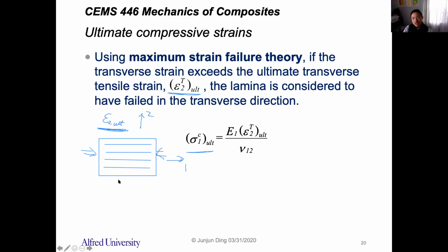which means the matrix or the matrix and fiber bonding fail, right? So let's see if this is the ultimate tensile strain of the matrix, right? So you don't want to exceed that. So by using this strain, you can calculate the maximum stress can be applied in this direction, right? So that's the ultimate strength of the composite in the transverse direction. So this is based on the failure mode of the matrix, right?